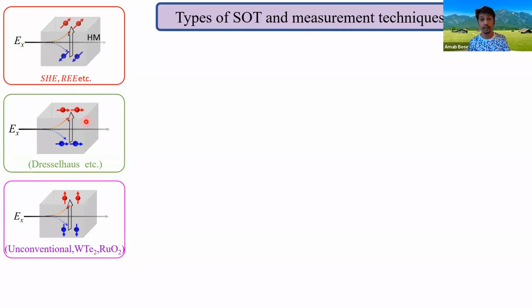We can also have this situation where the accumulated spins are polarized along the direction of the electric field. This typically happens in systems where we have Dresselhaus-like interaction. The third possibility is that we can have a generation of out-of-plane spins flowing in the out-of-plane direction. This is referred to as unconventional spin current, reported in some of the single crystal materials.